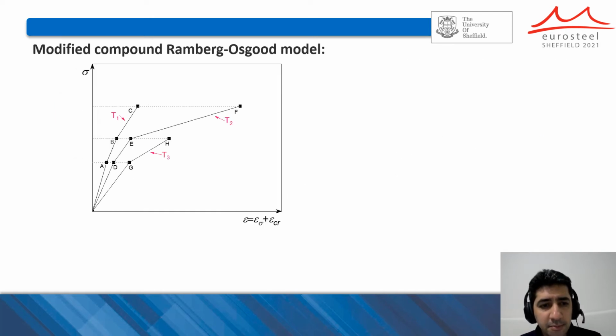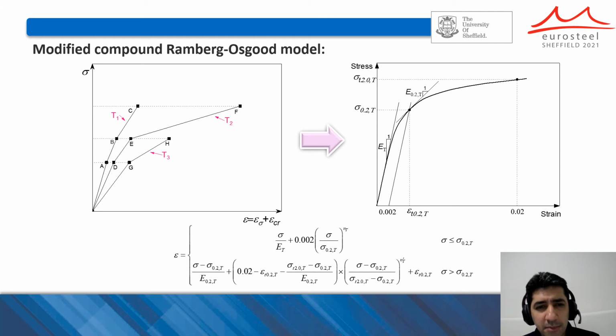Now that we have obtained the multilinear stress strain curves, they might be somewhat difficult for designers and engineers to utilize because they prefer mathematical models. To this end, the modified compound Ramberg-Osgood model, which has already been developed for the behavior of stainless steel at elevated temperatures, was fit to the multilinear stress strain curves.